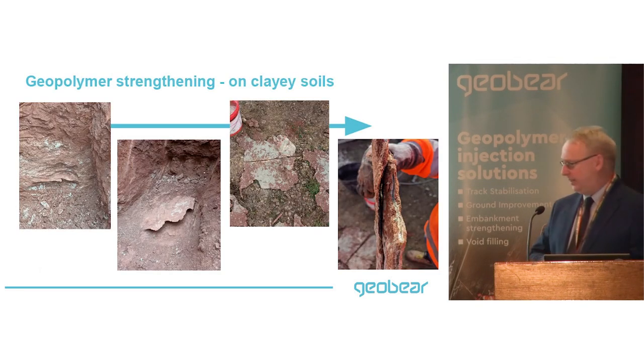Here's some pictures from an excavation we did. This was actually done in a stiff clay, and it showed how the polymer migrated along an open fracture. We dug it out of the ground, and it looks like this - that's an actual slab of polymer that's the same shape as the fracture it migrated along.